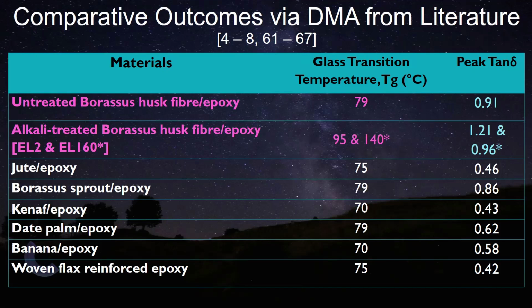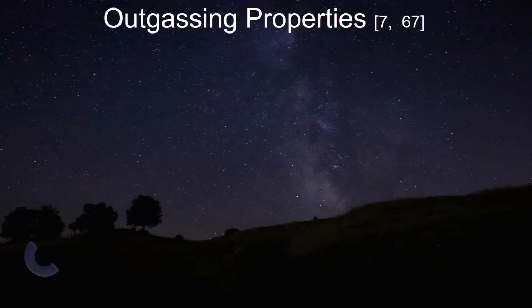Then we looked into the literature, and we found that the rest of the jute epoxy, Borassus sprout epoxy, and kenaf epoxy values were actually less than what we found. Even the damping factor. So that's why it's a bit of a promising result we found experimentally. Then we did the outgassing test.